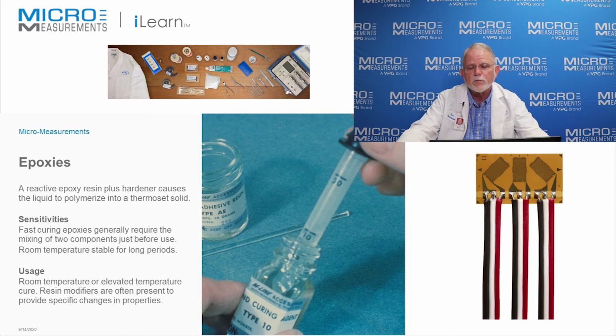The epoxy systems are famous for their high elongation capabilities too. At room temperature, AE10 can do between 6 and 7% strain easily, and AE15 will do up to 10% strain at room temperature. We're understanding that 1% strain is 10,000 microstrain. That's a lot of strain. You're doing some sort of post-yield study, likely as not, or a very low modulus material.